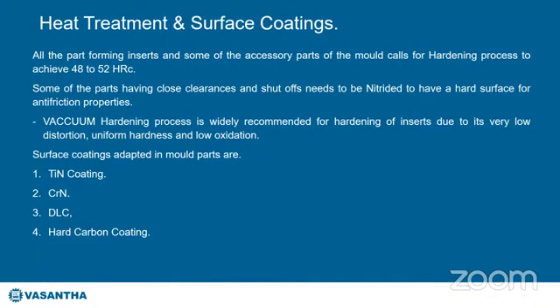The hardening process is done using a vacuum heat treatment plant, which we have seen in the video by our MD Shri Dayanand Reddy Garu. Vacuum hardening is widely recommended for hardening of inserts due to its very low distortion, uniform hardness, and low oxidation. After hardening, there are some coatings we can adopt in the mold parts, like TiN coating, CrN coating, DLC coating, and hard carbon coating.